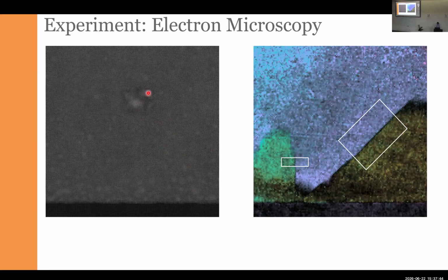Notice that the image is, of course, imperfect. These are the defects that formed as the result of the FIB preparation. Interestingly, they don't affect the polarization analysis. If we find all the atoms in this image and calculate the polarization fields, you start to see an image like this. This image and this image are the same; you just visualize the polarizations. You can see that some of the domain walls are very nice and sharp, and some of them are much more diffuse. If it is diffuse, that probably means that the wall is not aligned parallel to the beam. It's tilted in the beam plane.